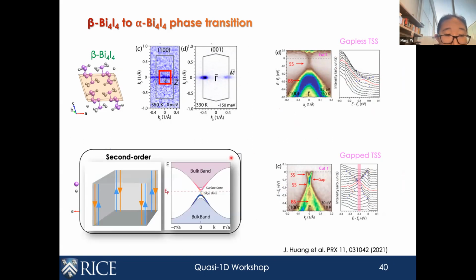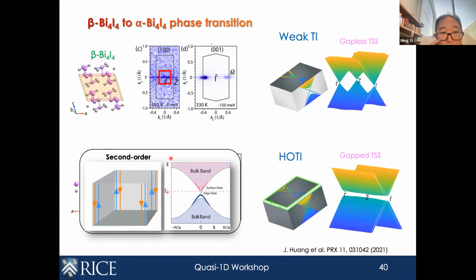So this is really consistent with our understanding of the behavior of a second order TI, which means that due to the dimerization of the crystal, we have an opening of the gap in the surface states, and we expect that within the surface state, there should live the hinge states. And from photoemission, this is really difficult to resolve, to look at the edges with that fine spatial resolution. But at least what we can resolve is the gapped bulk state and the gapped surface states, which would be consistent with the understanding that the alpha phase of bismuth iodide is actually a second order TI.